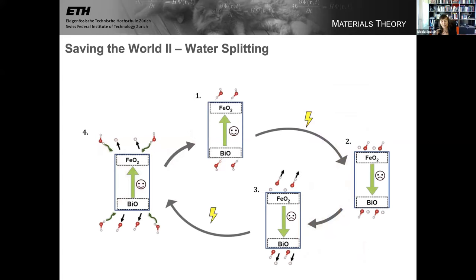So you could then envisage a cycle for effectively water splitting, in which when the bismuth ferrite slab is happy, water molecules adsorb on the surfaces. You switch it, for example, with an electric field. The water dissociates into the ions, and the positive ions stay on the negative surface. The negative ions stay on the positive surface. So we have a very effective way then of splitting the water into its constituent ions.